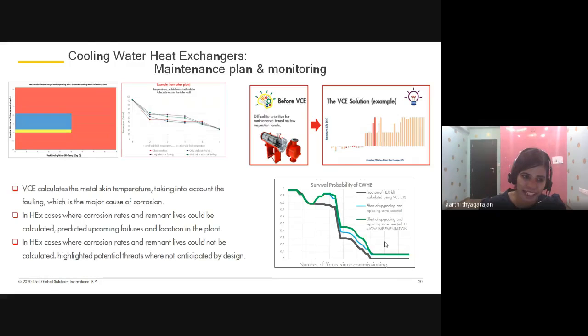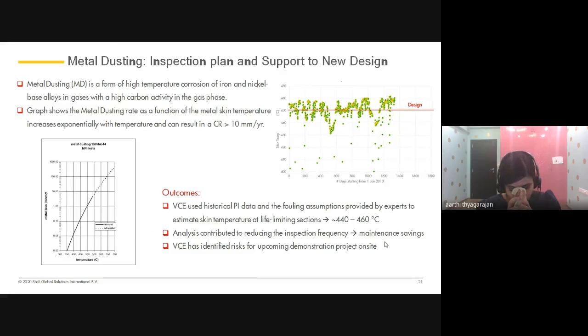Next slide, please. So this is a second example or a second mechanism in VCE. First, let me please address what is metal dusting. This is a catastrophic form of corrosion affecting iron, low and high alloy steels, specifically nickel or cobalt based alloys exposed to either reducing or highly carburizing gases such as carbon monoxide with carbon activity more than 1 and at elevated temperatures of 400 to 800 degrees Celsius. So this slide is about a famous mechanism called metal dusting.